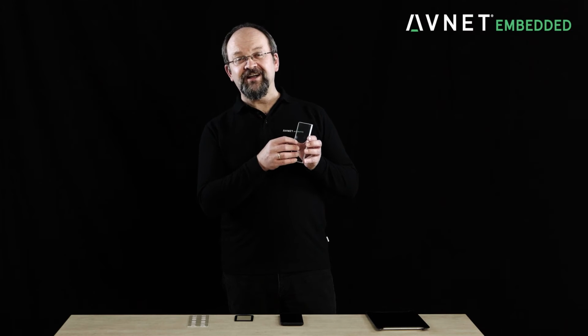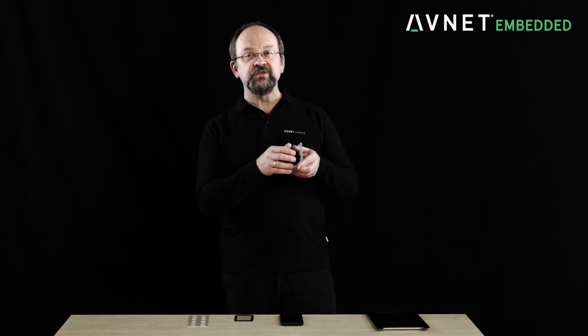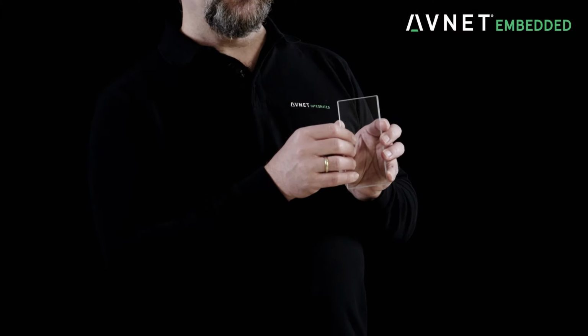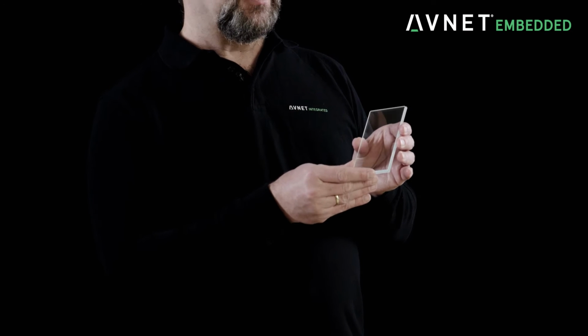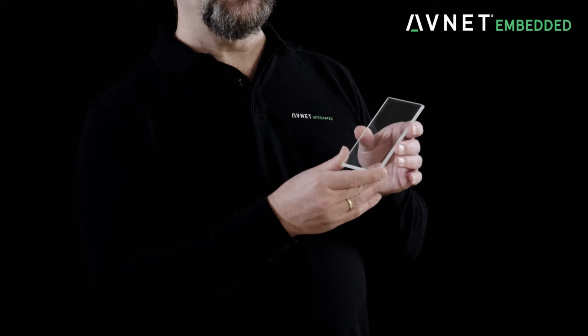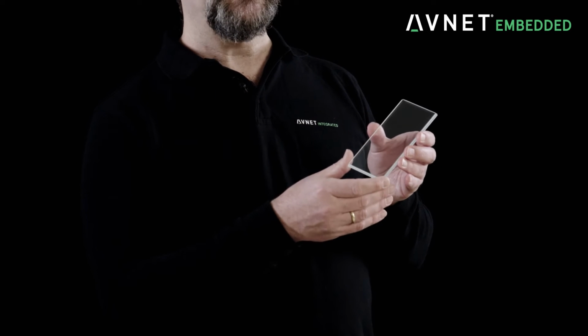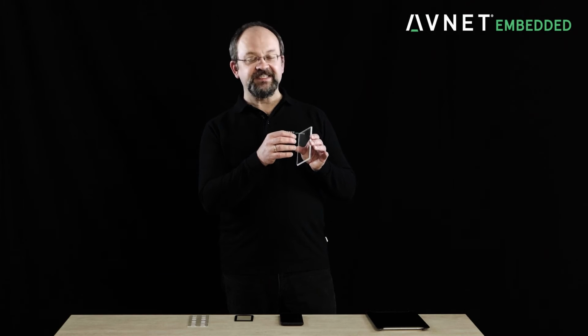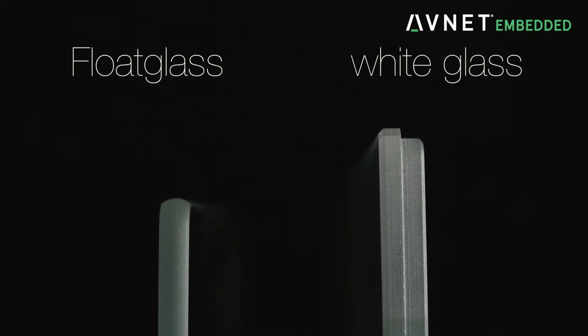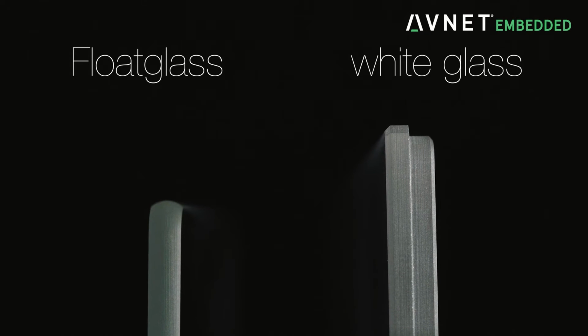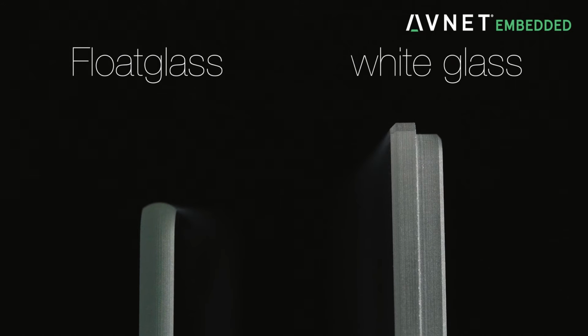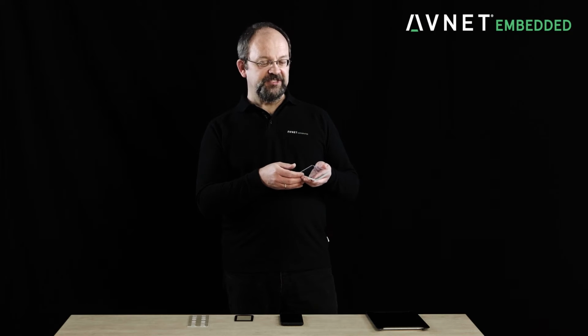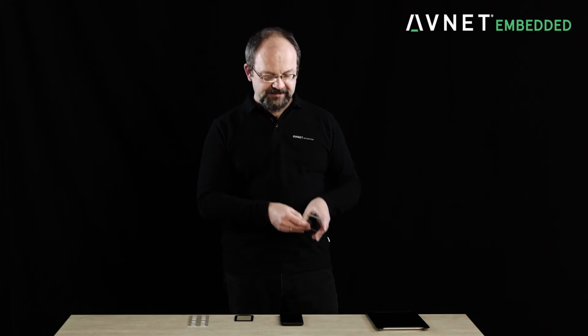To allow true color on a display, you can use so-called super white glass. Super white glass is a special mixture of the components. It has less iron oxide inside, and it doesn't tint what is behind the glass in a greenish color. So this can very well be used in medical applications and imaging applications, and you will get exactly the color you like.